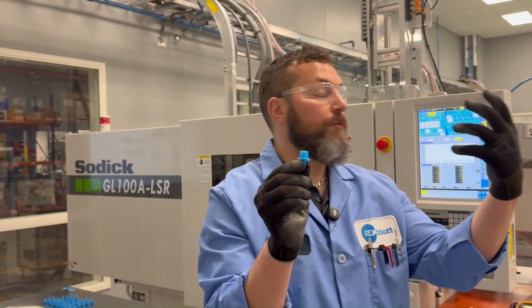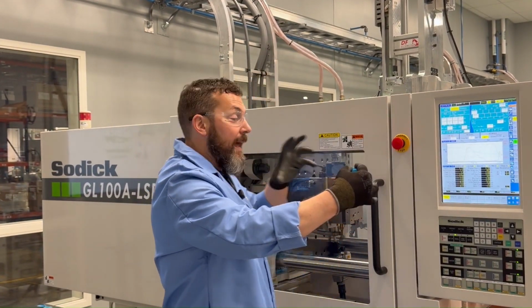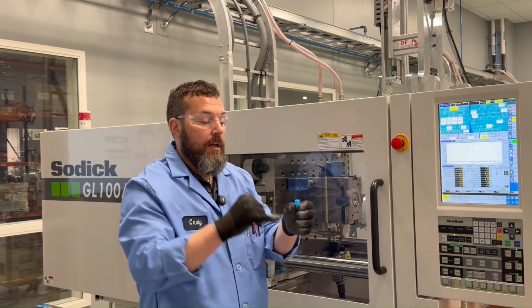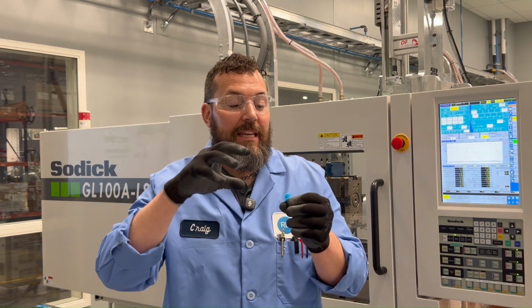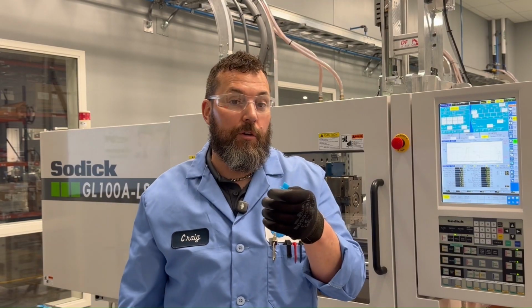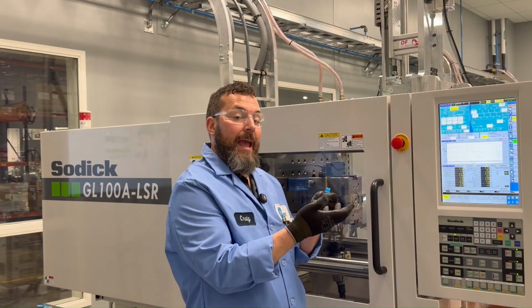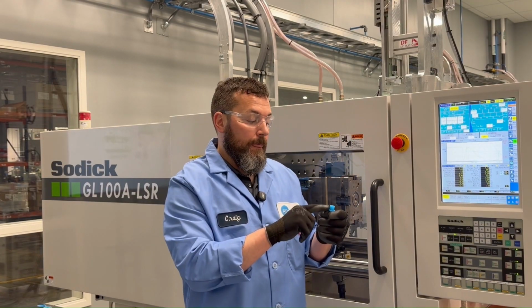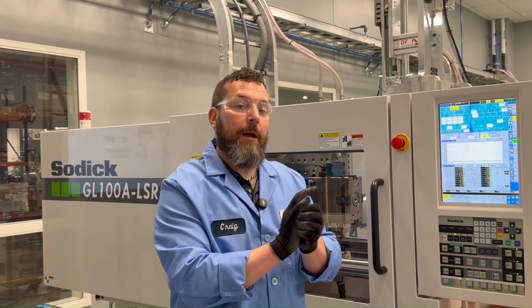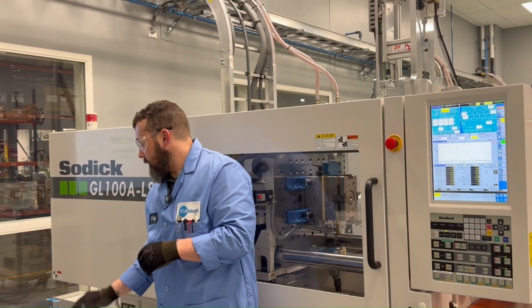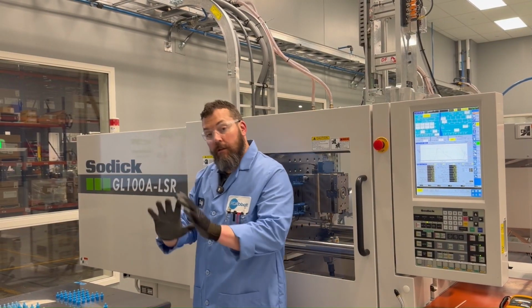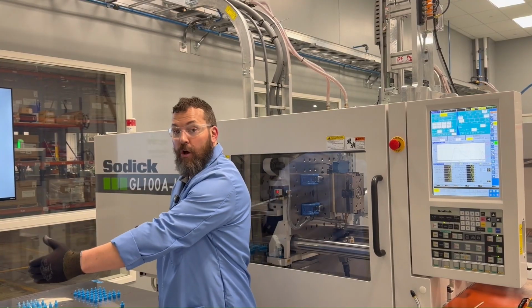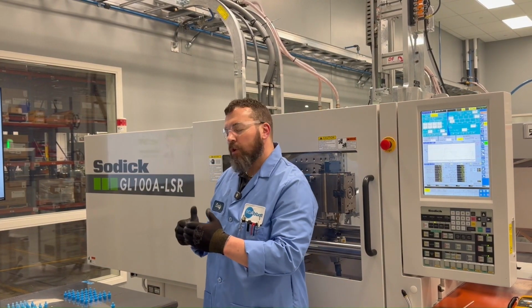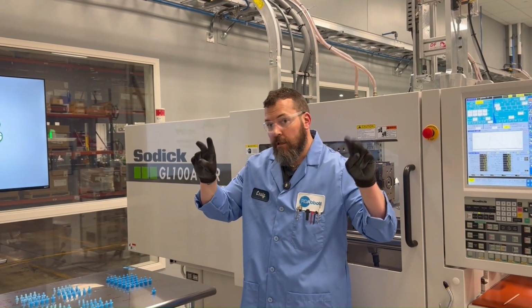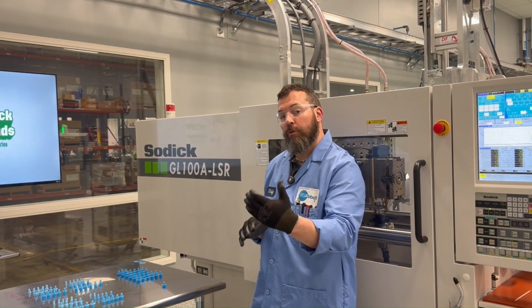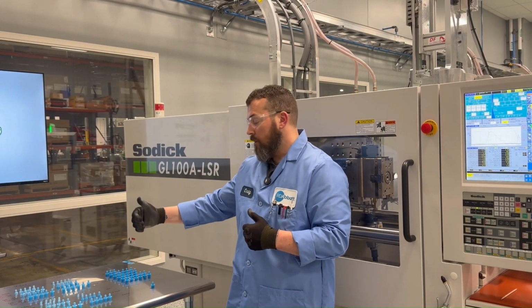So as we are utilizing vacuum in this mold, we are trying to evacuate out the atmosphere, the air that's in that cavity. That is actually air in the cavity that is superheating and exploding back into the material. So as much hold pressure as I'm adding, I'm really not filling the part out. And that's another problem because of how much back pressure is pushing against me. So as I'm going through this iteration of fill, after we did the fill study to find out shot volume, to find out consistency, you could kind of look at this as almost a freeze study in thermoplastics. We're not utilizing hold or hold pressure for that. I want to do that with my injection